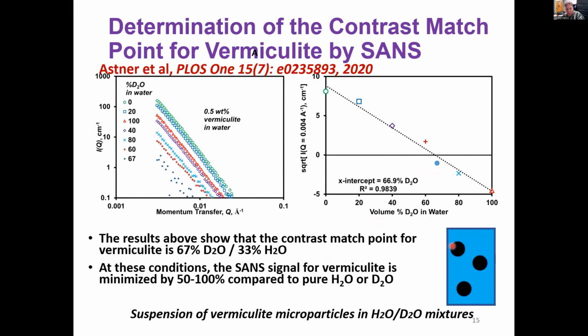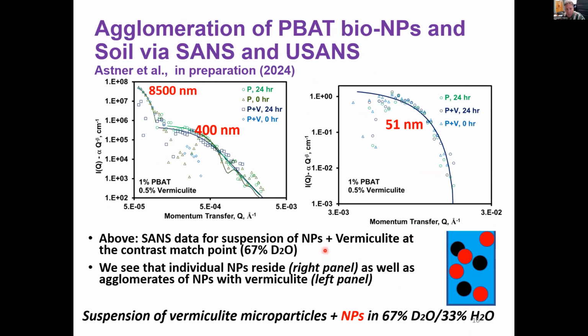And we used vermiculite in this particular study. And so at that level of deuteration, the signal due to the soil, again, is very small. And then we can operate at the contrast match point and look at nanoplastics and how they interact with soil, and do work with modeling of our data. This is a spherical model at about 50 nanometers. And then we can do what's called USANS. It's a lower Q range, higher length scale that we can do some analysis work on. And for instance, we see that nanoplastics that are smaller tend to not undergo agglomeration, and then larger ones do.